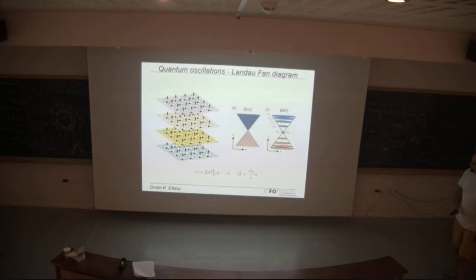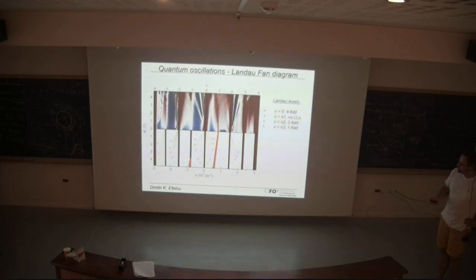So if we measure the data which I was about to show, what we expect from Landau levels is linear lines in this type of measurement. We measure resistance as a function of a perpendicular field, and as you can see, from the different integer fillings we observe these linear lines.